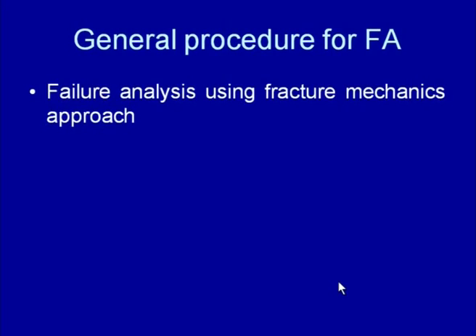So, fracture mechanics basically helps to establish whether a given size of crack or discontinuity should have been stable or not under the given load service conditions and for a given set of material properties, because fracture mechanics nicely relates the material properties, the external service conditions, and the discontinuities present in the given material. So, for a given size of discontinuity in the material, for the given service conditions, and given fracture toughness of the material, and given stress conditions, should it have performed successfully or not. That kind of failure analysis is performed using the fracture mechanics approach.